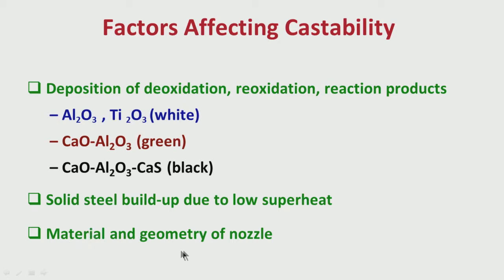The desirable superheat is around 10 to 20°C. Too much superheat leads to undesirable coarse columnar grain cast structure, while very low superheat risks solid steel build-up affecting both cleanliness and casting continuity. The material and geometry of the SEN are also very important — port angle (horizontal, upward, or downward), diameter, and shape (circular or elliptical) all matter. Modeling can help decide the optimum SEN design; a poor design can cause castability problems and interruptions during continuous casting.